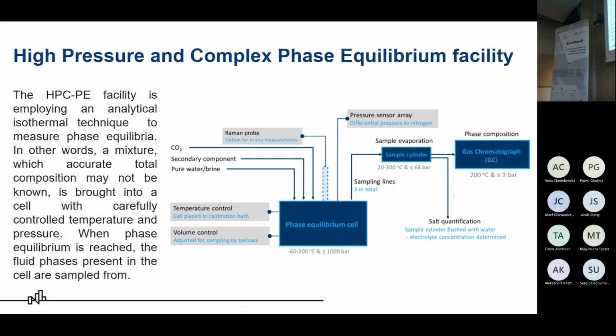It's brought into a cell with carefully controlled temperature and pressure because the cell is submerged in a calibration bath in hot oil, so we can control the temperature and we can control the volume and the pressure using bellows. When phase equilibrium is reached, the fluid phases present in the cell are sampled from the GC.